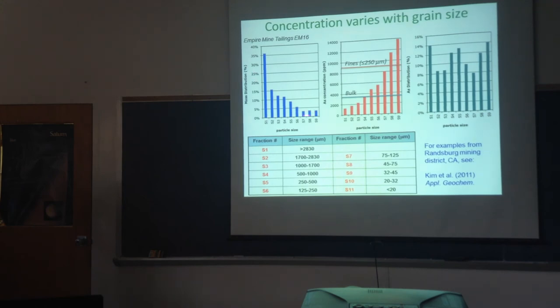So you have a relatively small amount of this fine grain material, but when you look at the arsenic concentration of it, the fines have a lot higher concentration of arsenic than the bulk. The average bulk of this particular sample had about 3,500 ppm, so it's one of the higher ones, but the average fines were like 9,000 ppm. So it's really important to understand what's going on in the finer grain material.